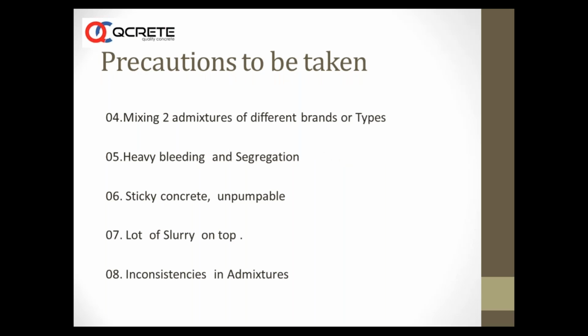We need to be careful when using two admixtures, because sometimes you have a PC admixture on plant and sometimes another admixture, maybe SNF. PC and SNF are not compatible. You should not mix a PC admixture or any admixture with a waterproofing admixture without doing a trial.